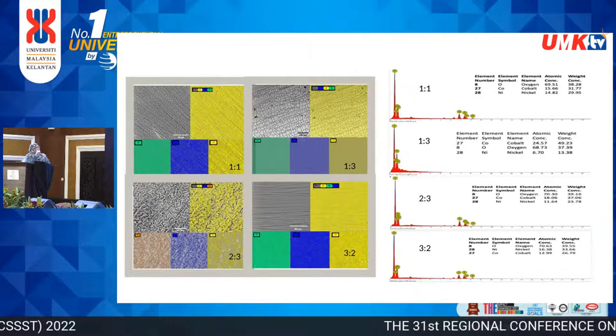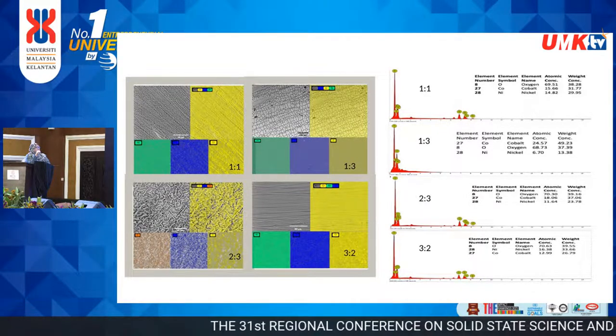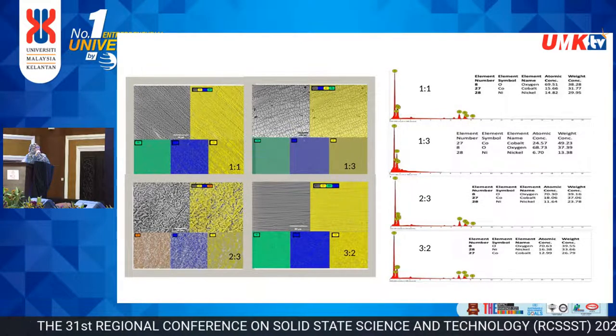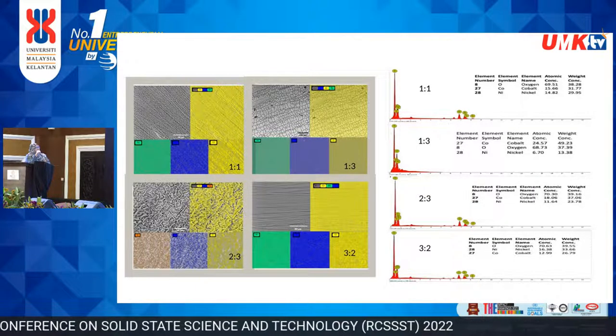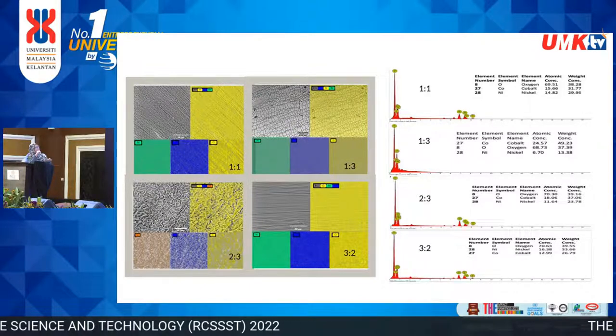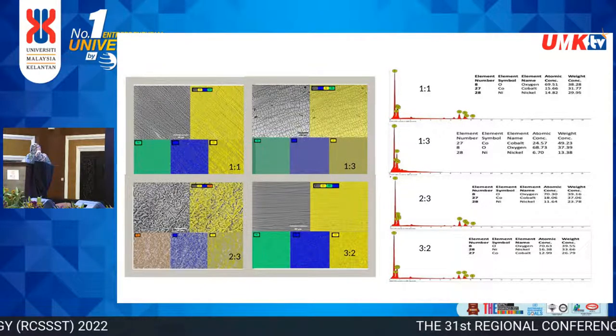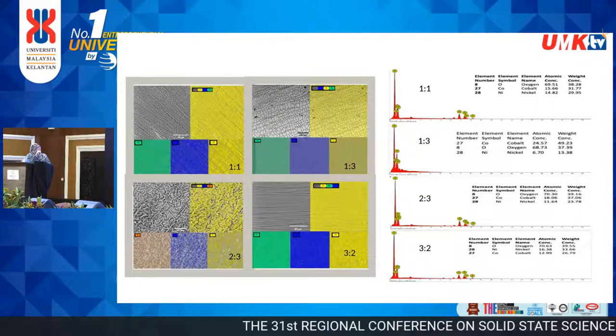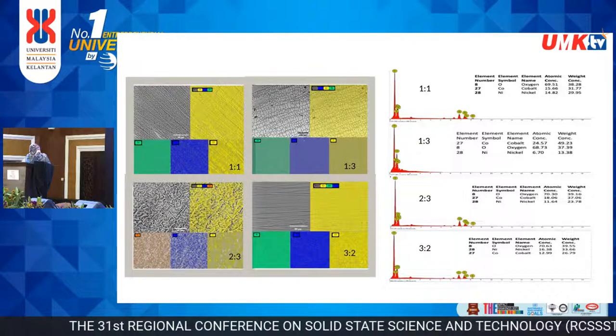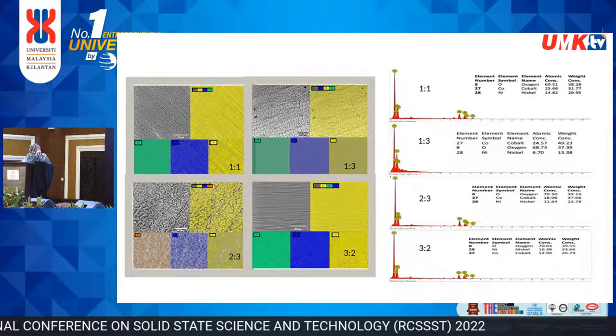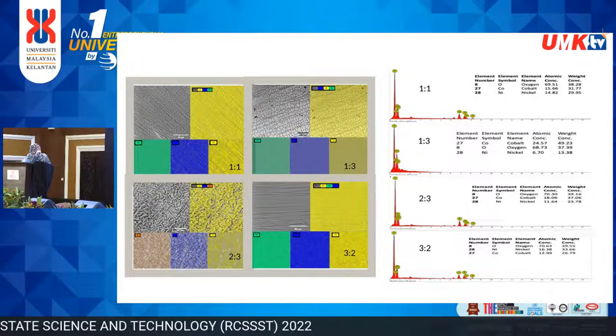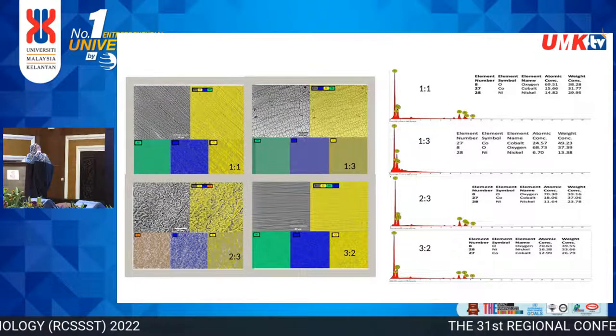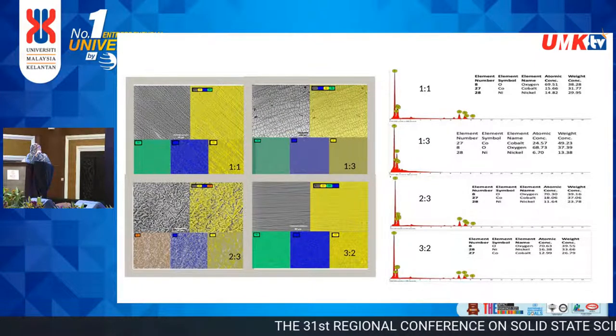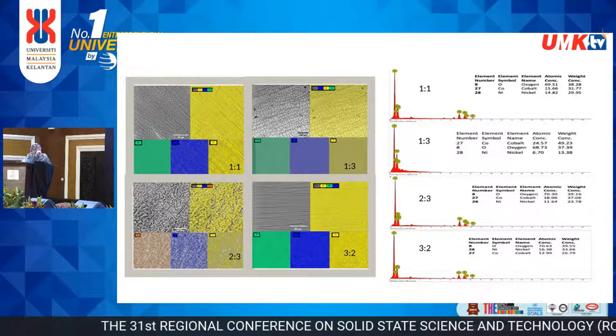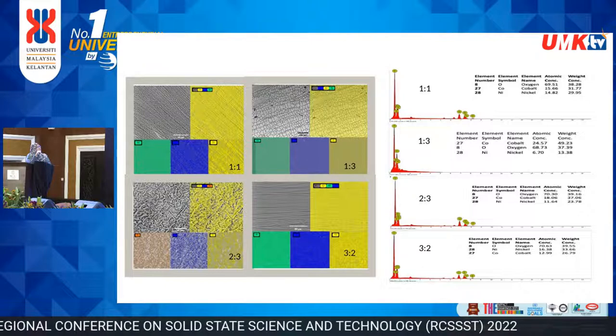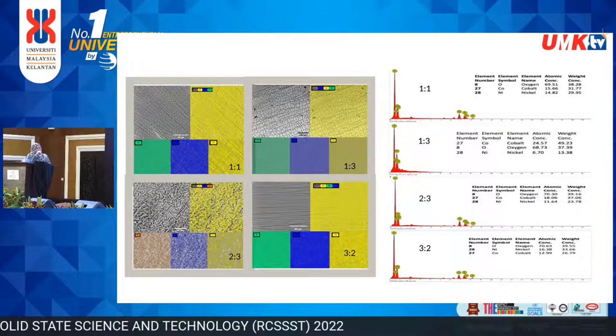Okay, this is the SEM micrograph at low magnification because we want to see whether the sample is well distributed or not. We can see that nickel and cobalt are well distributed. And then we can see from the EDX that the weight concentration is similar to the nickel cobalt electrolyte prepared prior to electrodeposition.